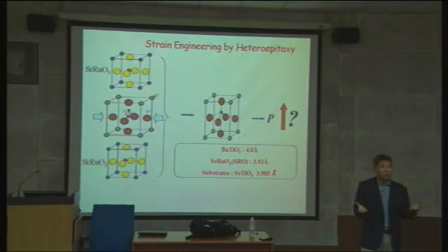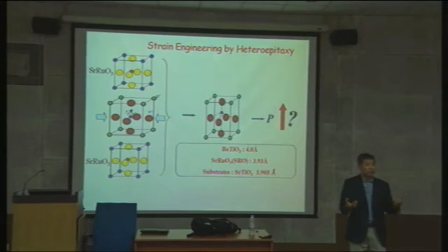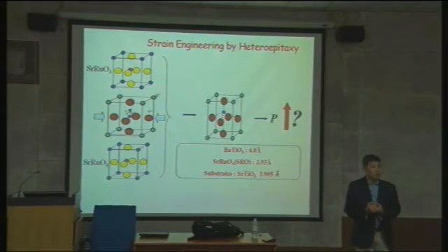Exactly, yeah. So that's also something on one monolayer iron selenide, whose superconducting temperature, one group claims, is like 100 Kelvin. And the bulk material is less than about 10 Kelvin, very low. It's still being debated whether it is 100 Kelvin, but at least people agree that 50 Kelvin superconductivity is a significant enhancement, and it only happens in one monolayer iron selenide. And that is either a dimensional crossover or interfacial superconductivity, which is another issue of the physics. But at least we can go thinner and thinner. At some point you have something new. The same with nanoparticles: silicon nanoparticles are not optically interesting, but gold nanoparticles are very interesting in terms of optical properties.